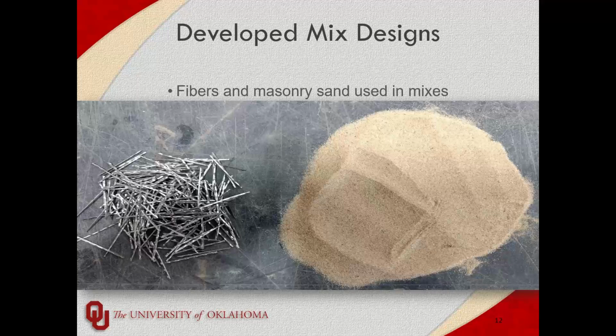They are about 1 inch long. They're meant for refractory concrete. But their weight did cause us some problems because they are much heavier than the Dramix. So we ended up having to adjust our high range a little differently, so that we could maintain a flowable mix and maintain suspension of those fibers, as opposed to adding too much high range and then having them all sink.